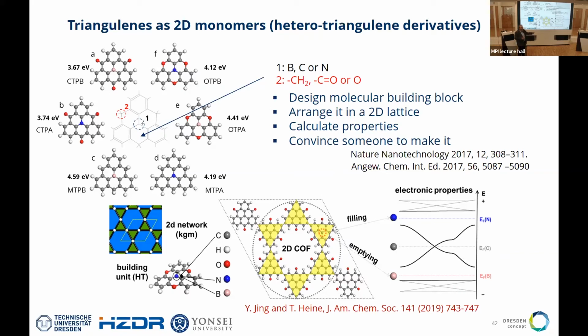That means you take away 1 electron per building block. That means your Fermi level moves down. Now you have a flat band that marks the valence band maximum. That means you have very, very heavy holes, and you have very mobile electrons. Okay, if you replace the carbon with a nitrogen, you do exactly the opposite. You completely fill this Dirac band with electrons. You put the Fermi level here. Again, you now have very mobile holes and very heavy electrons.